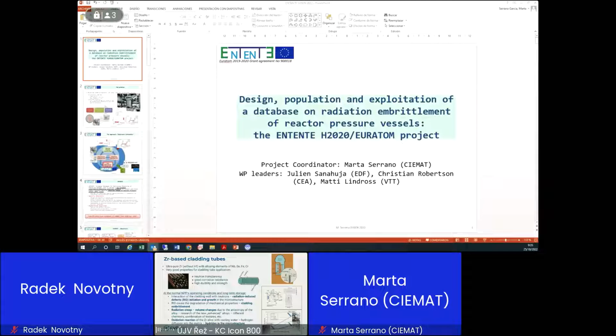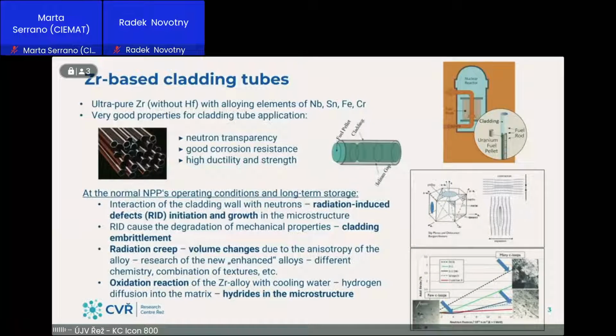What happens under normal nuclear power plant operating conditions and long-term storage? During the process, there is an interaction of the claddings with neutrons. So radiation-induced defects are created in the microstructure, and they cause degradation of mechanical properties. That means the material is hardened and embrittled. We can observe radiation creep, which means volume changes due to the anisotropy of zirconium alloys. And we can observe as well the oxidation reactions of the zirconium with cooling water, and hydrogen diffusion into the matrix, which we analyze as hydrides in the microstructure.